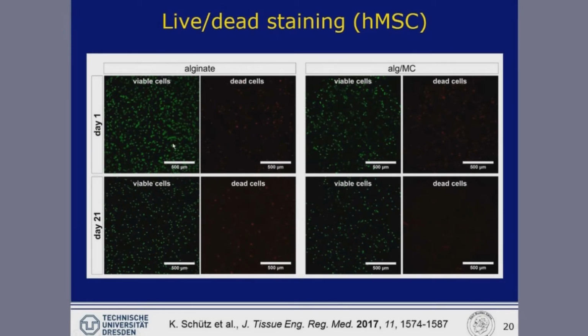Again, comparison between the pure alginate used by many groups worldwide and our novel blend. Upper row of images is day 1, so directly after printing. Lower row is after 3 weeks of additional cell culture. And for better visibility, we have separated the channels. So we have the live cells with green fluorescence in the live/dead staining, and the dead cells showing red fluorescence. Only very few red cells in both cases, and maybe even a little bit fewer dead cells after 3 weeks of culture in our new blend compared to the pure alginate.